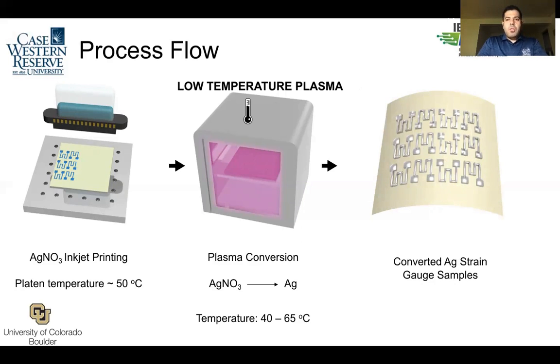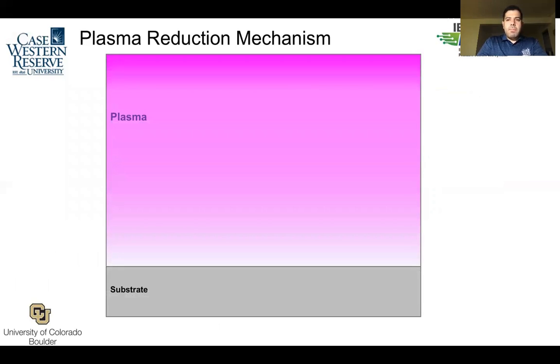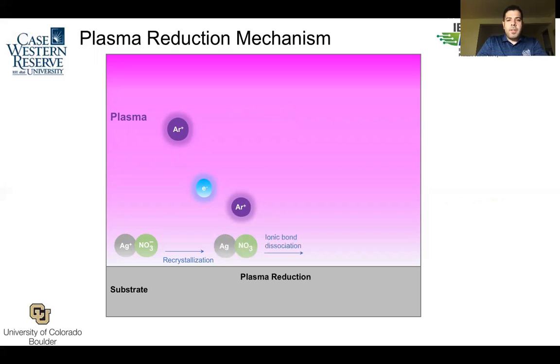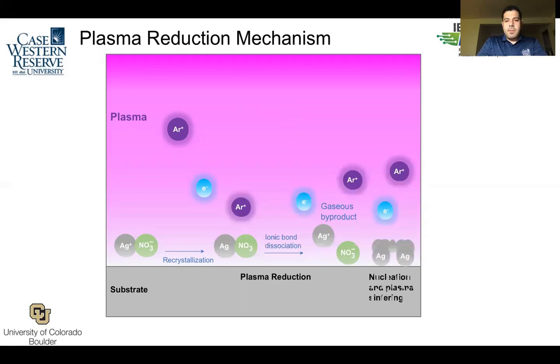silver ink samples. So very briefly, if you want to know what really happens during plasma reduction, here you have a plasma and a substrate. We put our silver ink sample, which is silver nitrate dissolved in ethylene glycol. First you have the silver nitrate, ionically bonded, and then first they recrystallize, and the argon plasma is an ionized gas. The argon plasma hits the silver nitrate, and that will cause ionic bond dissociation, in other words, plasma reduction. With the addition of electrons, the nitrate evaporates, leaving ionized silver atoms behind. And with the generation of secondary electrons, the silver atoms nucleate and sinter. The longer the plasma exposure time, the greater the nucleation and plasma sintering.